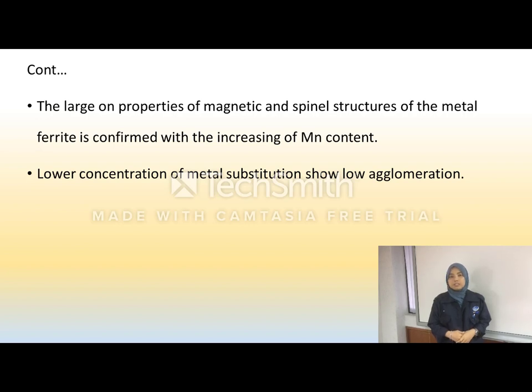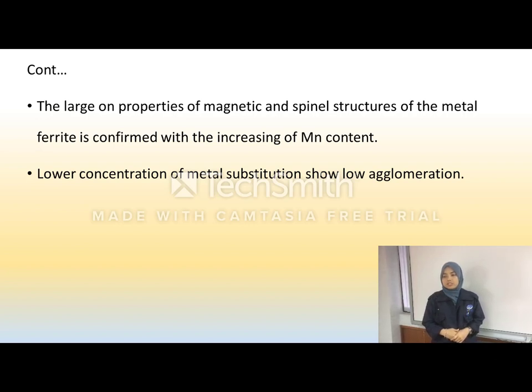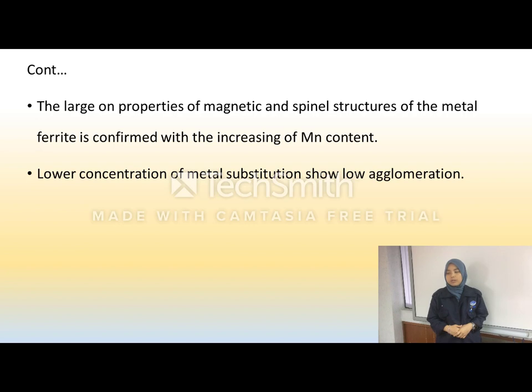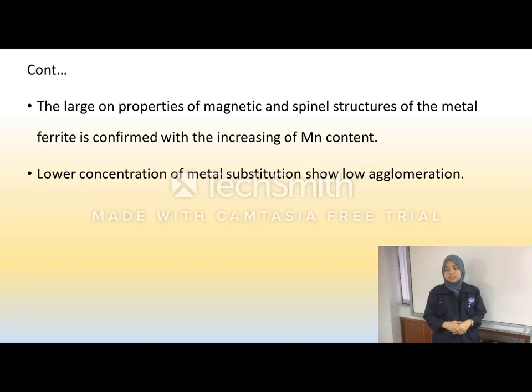A larger effect on the magnetic properties and spinel structure of the metal ferrite is confirmed with the increasing manganese content. Besides, clear and homogeneously dispersed grains can be seen from the image, and also well defined sharp edge grain boundaries. A small amount of intergranular pores was shown in high substitution of manganese compared to low substitution of manganese. As a conclusion, a lower concentration of metal substitution shows lower agglomeration and better order, and also a smaller particle size distribution than the higher metal substitution.